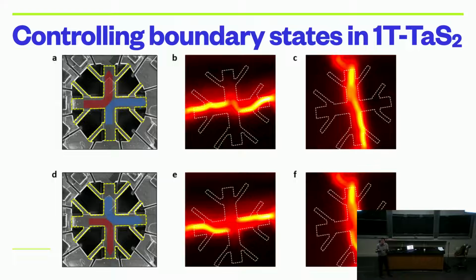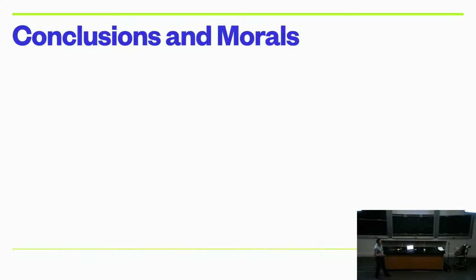But we still actually have no idea what the boundary is made of, like whether it's the metal insulator boundary or what exactly it is. But again, this happens at very low currents, very low powers, and it just goes to show, in terms of the conclusions and morals, if there are any, that we start from an idea, which is exotic systems near critical points, connected to this really abstract problem of understanding high-temperature superconductivity.